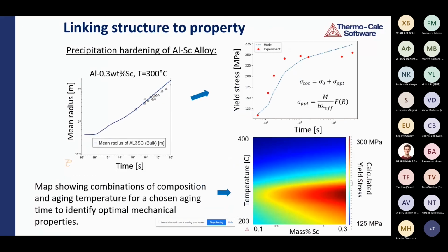Here we have taken the results from a simulated microstructure, that is the amount of precipitates and their size, and then we use that as input for predicting the yield stress as a function of aging time at the given temperature. Then you can see in the upper right diagram how this yield stress corresponds to the experimental values. And the colored diagram at the bottom shows a prediction for the yield stress as a function of scandium content and aging temperature for a given aging time. And all these kinds of simulations are quite important if you design a new material or a new process, for example.